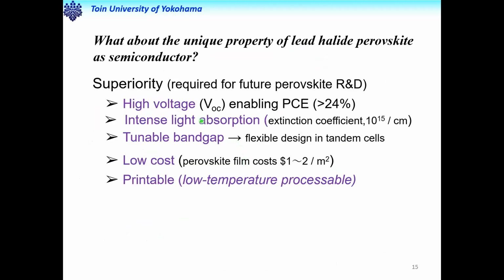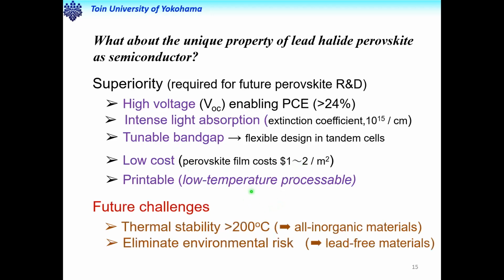So what is the advantage? Simply, the output voltage from the solar cell is relatively large. This has been enabling high efficiency of solar cells. Light absorption is very intense, and we can change the band gap. So the band gap is tunable, and the cost is very, very low. Can you imagine the perovskite film costs just $1 to $2 per square meter? That's the material cost. All layers are printable, and low temperature processes are applied, but the future challenge is how we can stabilize the cell to ensure stability to 200 degrees.